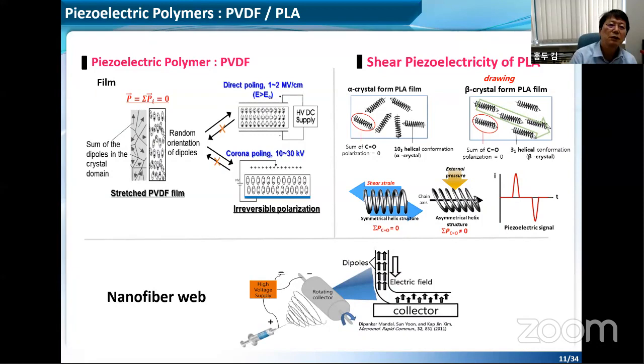A good example is PVDF, polyvinylidene fluoride. Another example is a biopolymer, polylactic acid, which is one of the well-known piezoelectric polymers. These two materials have some different characteristics. As you know, PVDF without any process cannot be a piezoelectric polymer system. Even if we stretch a PVDF film, it doesn't give us a piezoelectric signal. It's because the crystal domains are randomized, so the total polarization is always zero. In order to become a piezoelectric polymer, either direct poling or corona poling is required.